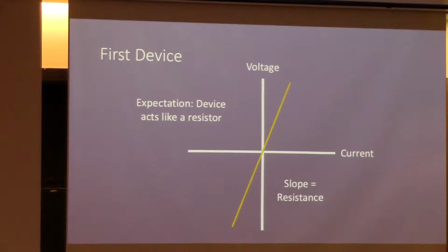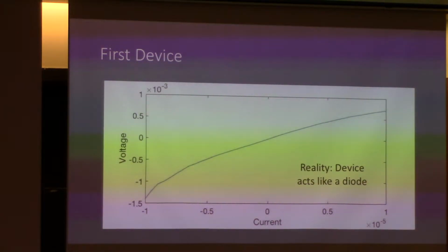But what we saw when we put this device in and measured its resistance is that it actually made a curve. Our device is acting like a diode. It's more resistive when the current goes one way than the other. So what this suggested to me is that our fabrication process is not as perfect as we thought it was. There must be some sort of impurity between the flake and the contacts.